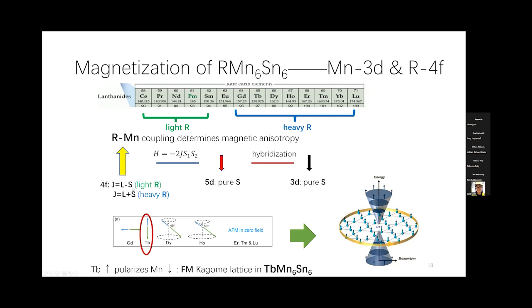So if you have a light rare earth, meaning your ground state is L minus S, it is ferromagnetic. Well, if it's a heavy rare earth, it's anti-ferro. Sorry, it's ferrimagnetic, meaning the rare-earth moment and manganese moment are anti-parallel. Fortunately, because the 4f local moment has very strong anisotropy, if you check the different rare earth elements, you find